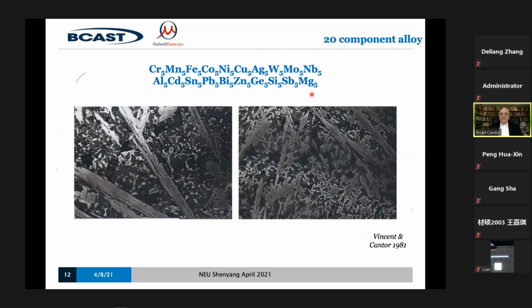And I made this actually, but then Alan did his project and he looked at it and it was a mess. You can see it was very brittle. It had lots of phases in it. The X-ray diffraction traces were complicated. It had lots of different phases, and it was a bit of a mess. And we weren't quite sure what to do next. But then we noticed that this background phase here consisted of just 5 components: chromium, manganese, iron, cobalt, and nickel. The first 5 here, in equal proportions. We noticed that in a scanning electron microscope when we did energy dispersive X-ray spectroscopy, and that was very surprising. In fact, that material is what Alan then began to look at.